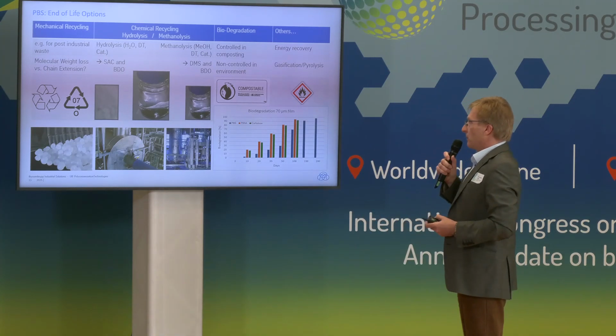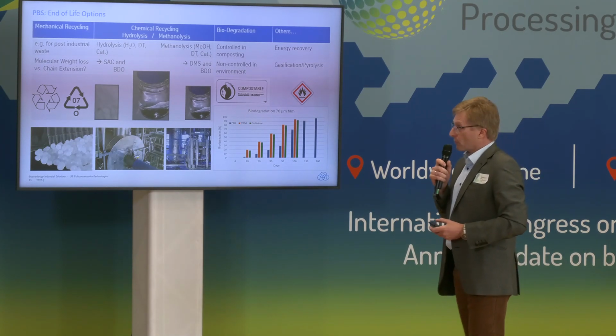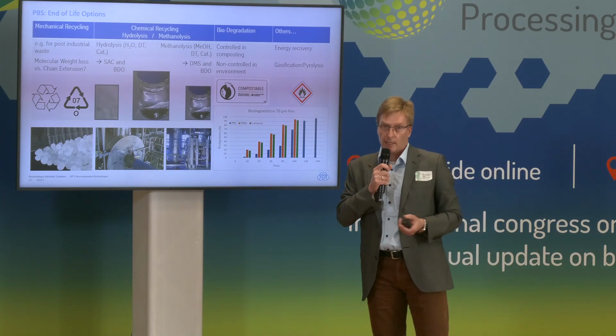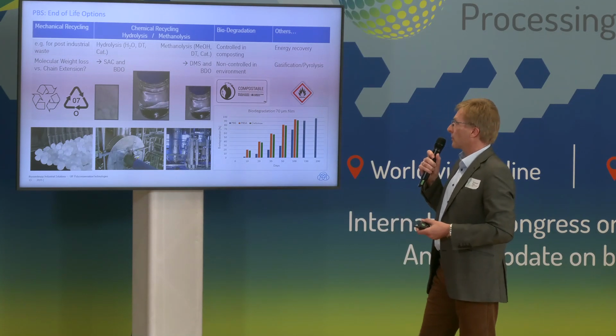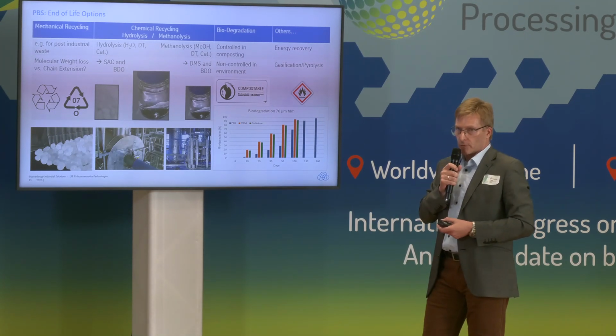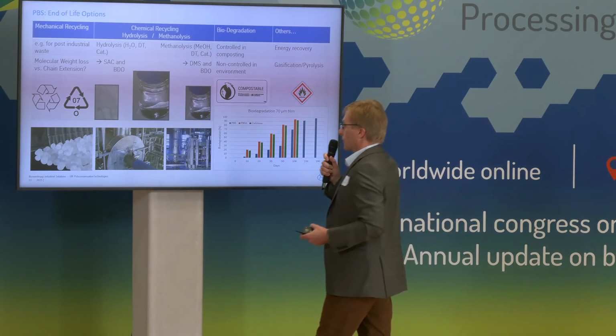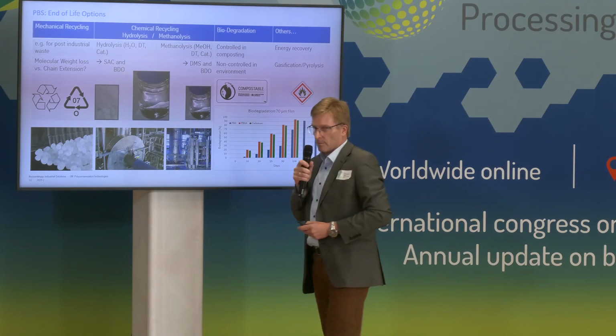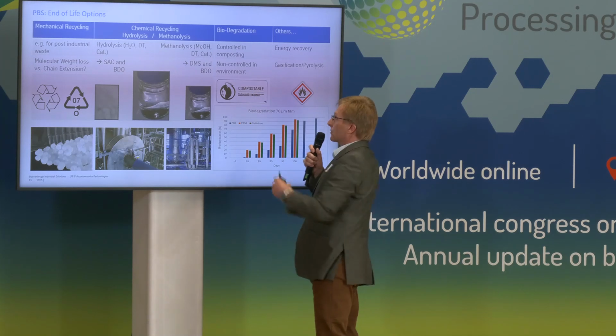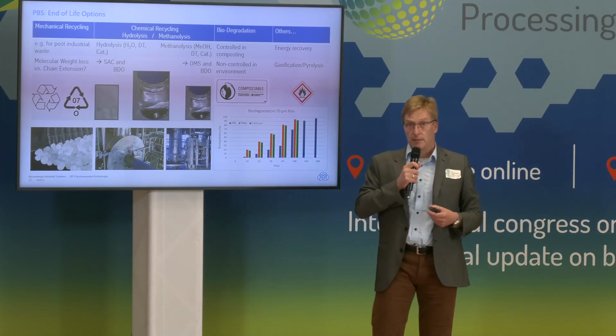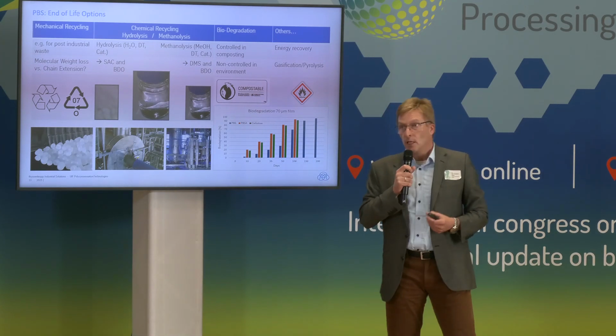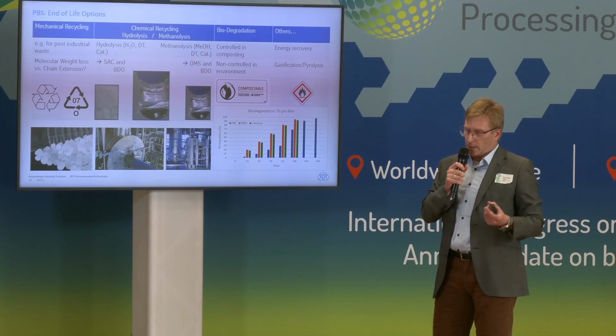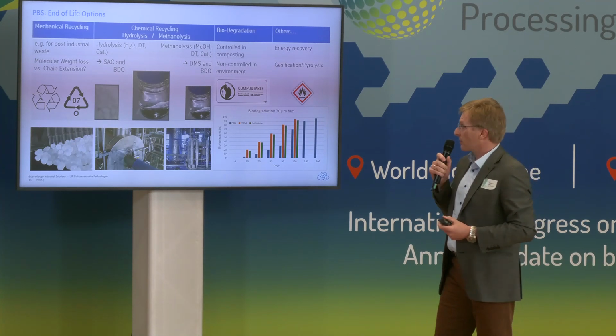On the other hand, PBS is also a very good candidate for chemical recycling because you can do easy hydrolysis, or you can also do methanolysis of the PBS to bring it down to the monomers. If you do hydrolysis, you end up with succinic acid and the BDO again. If you do methanolysis, you end up with DMS, dimethyl succinate, which is also a monomer, which you can again use for manufacturing of PBS.